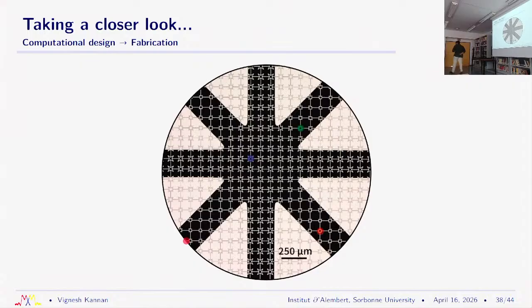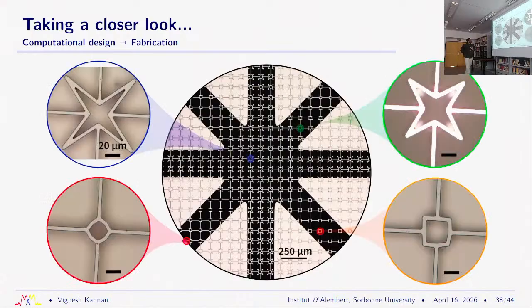In this case, we actually reduced our beam widths by half. So we have 5 micron beam widths and unit cell dimensions of 100 micrometers. If I zoom into specific regions of specific unit cells, you can see that we capture the gradient beautifully. In these samples, we had nearly 100% perfect beams. I don't have the quantification of the perfection of the unit cells, but maybe one of our devices failed, out of something like 5 devices, and pretty much all of our beams were perfect. So this is a very robust technique.